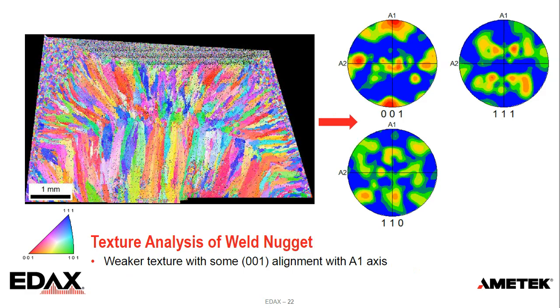I can also come in and crop. I did my best to crop the weld nugget, so it wasn't a rectangle. It's what we call a polygonal crop, trying to crop out those weld nugget grains. Looking at the texture of these, we see it's quite different. There's more of a 001 alignment along the A1 axis.